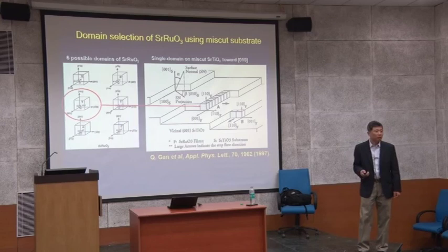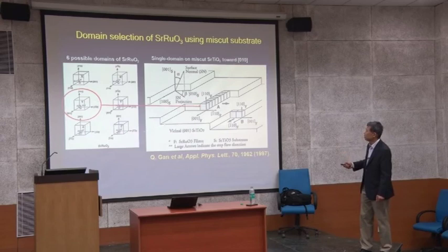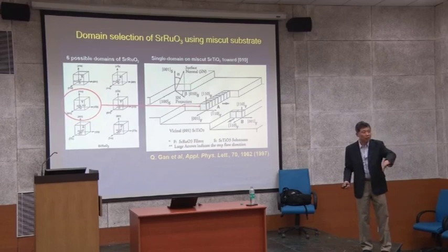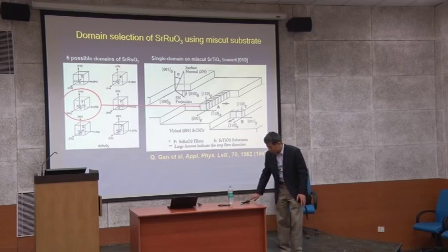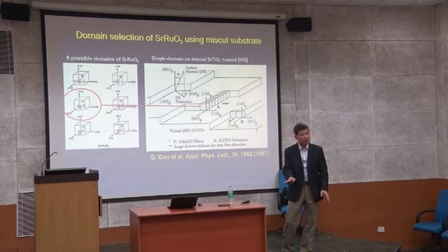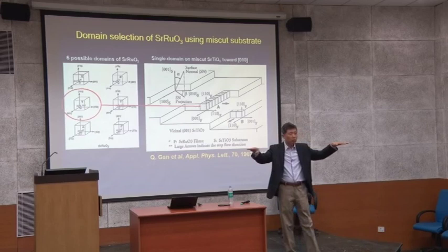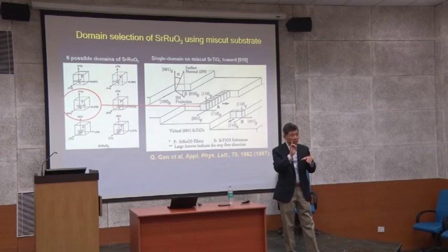But depending on how you prepare the substrate, like you mentioned the 110, it's not like this. The surface has a much higher miscut. When you have this surface, it is flat. But when you make the surface a little bit slanted, at a slight angle, we call this miscut. It's not perfectly parallel to the crystallographic plane. It's off from the crystallographic plane by a very small angle, not a high angle.